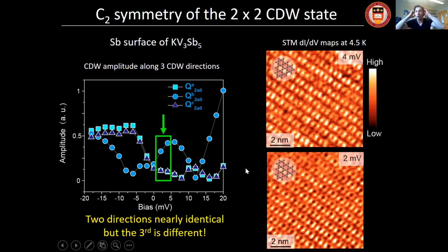Just to convince you a little more and to show what this looks like in dI/dV maps. What kind of unidirectionality am I talking about? If you focus on these few energies here, this is a dI/dV map at 4 and 2 millivolts. You can see that at about 4 millivolts, this is the higher point there. You get these nice unidirectional lines. This is exactly what one would expect based on one wave vector being much stronger than the other two.